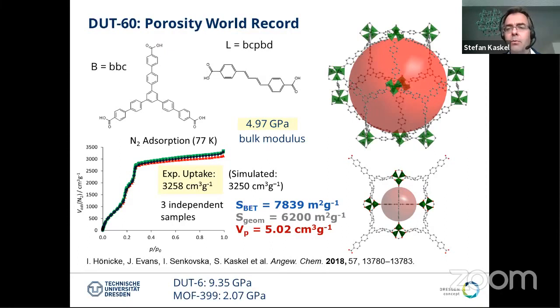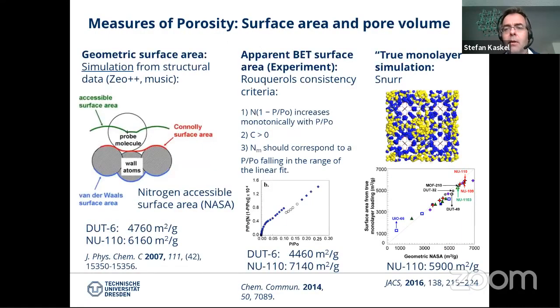But of course, these ultra-high porosity values also triggered a lot of debate. Is it really true? 7,000 square meters per gram? Is it real? These questions always come up and are very important in the field of adsorption. So these are, of course, only BET surface areas, which are apparent BET surface areas. They have an effective value. And Rouquerol proposed the consistency criteria to evaluate the BET surface area. And we tried to apply this also to the MOFs, but there are severe limitations, of course.